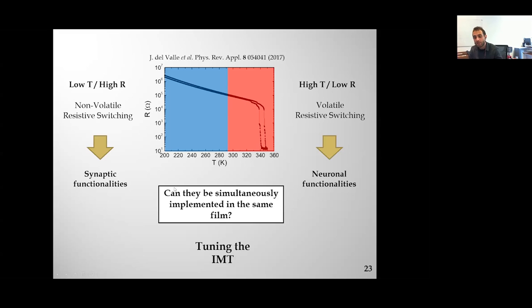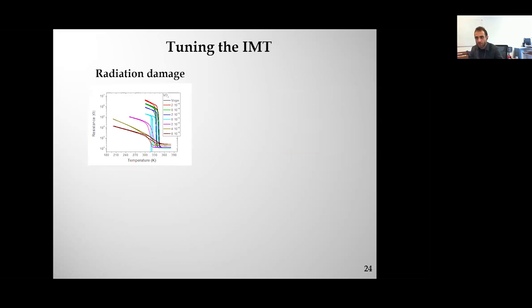And that gives us a hope. Maybe we can, in the same film and at a single temperature, implement both. So we can make a neural network in a single film in the same material. In principle, it would be possible if somehow you're able to move the position of this insulator to metal transition. If you are able to locally change where this transition is, you can bring it to lower temperatures. At a single temperature, you could have some parts of your film behaving as a synapse and some parts behaving as neurons. But for that, we have to be able to tune the insulator to metal transition locally. So we are looking at different approaches for that.